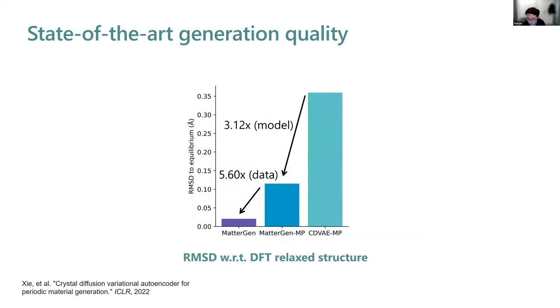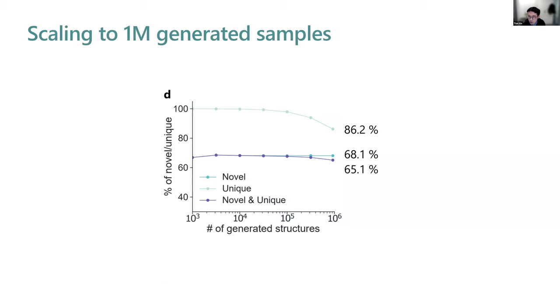In addition, we also looked at the RMSD of the structures that we generated compared with the DFT relaxed structure. So in here you can see the number with the unit of angstrom. You can see again with model improvements, we see a three times drop, whereas with data improvements, we see like a 5.6 times drop. So at the end, our RMSD is very small for the generated materials with respect to DFT relaxed structures.